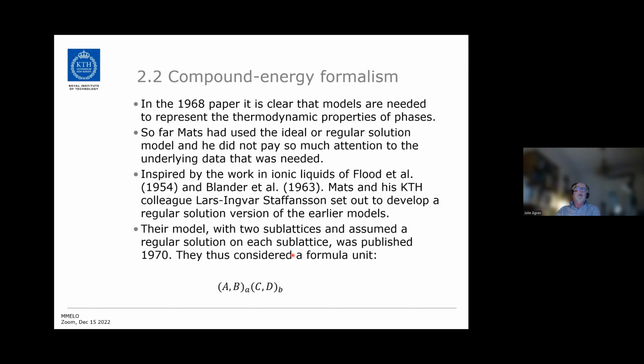In the 68 paper, it is clear that models are needed to represent the thermodynamic properties of phases. Until then, Mats had used ideal solutions or possibly regular solutions. And he did not pay much attention to the data you needed in the models. And then he was inspired by the work on ionic liquids by Flood and by Blander. So he and his colleague, Lars-Ingvar Staffansson, started to develop a regular solution model which would cover those earlier models. And it was based on two sublattices, and it was published in 1970.